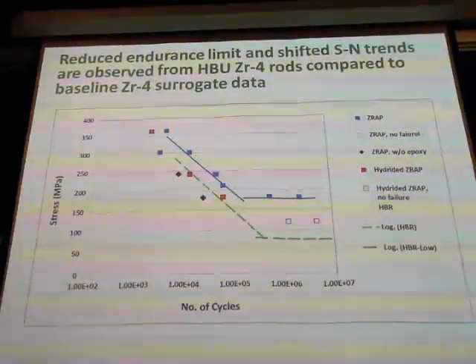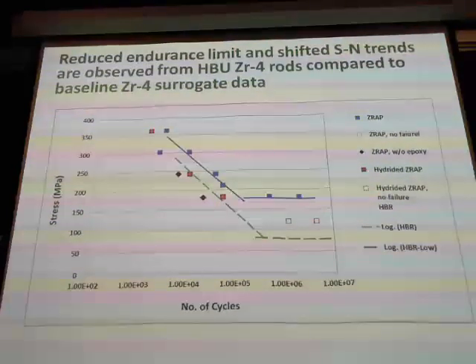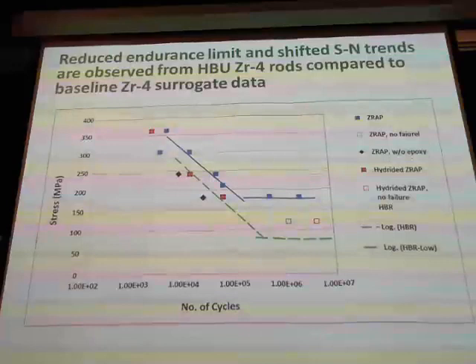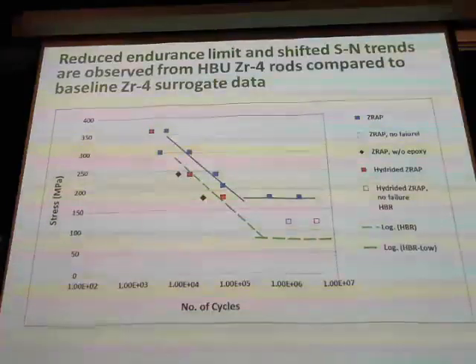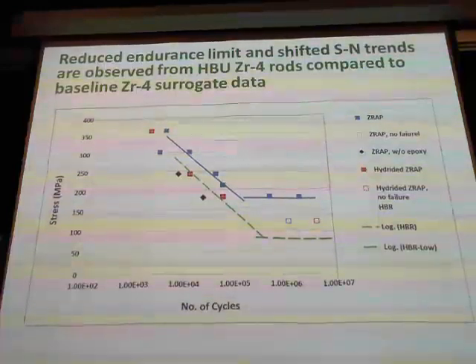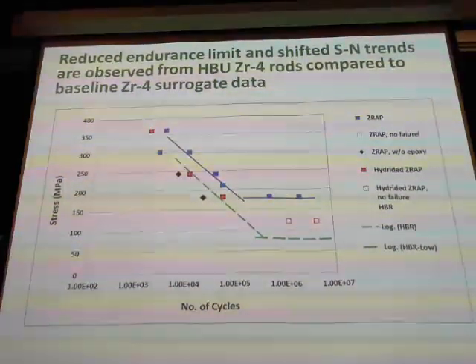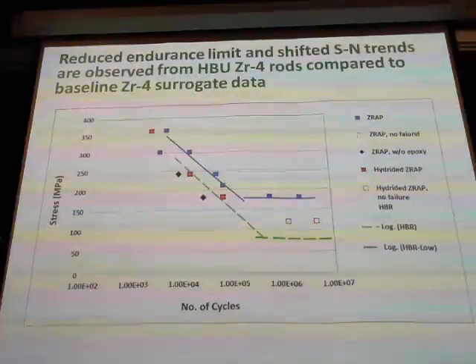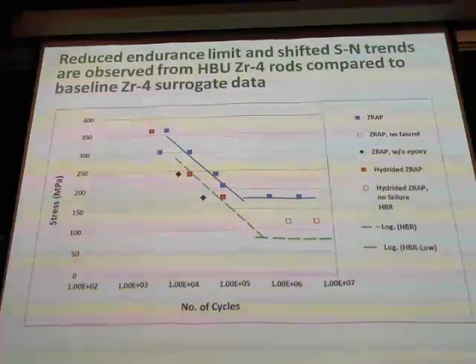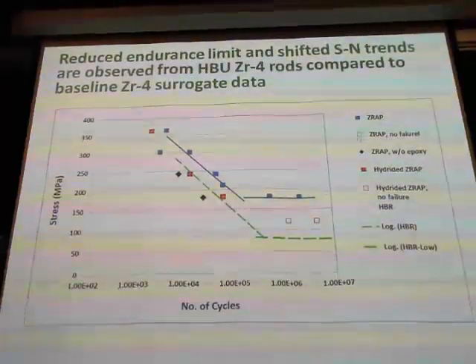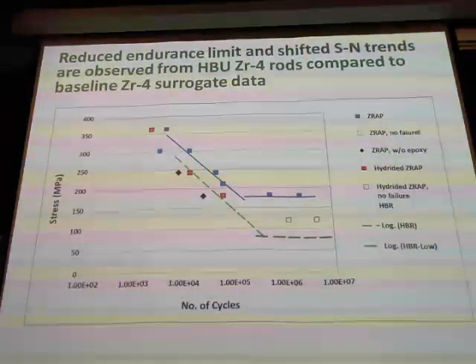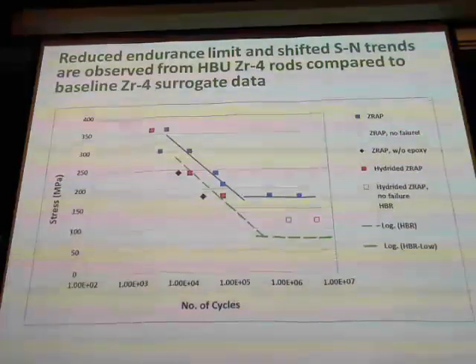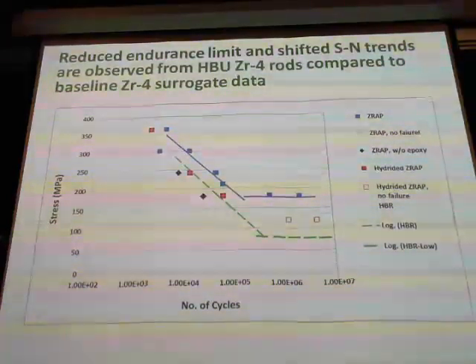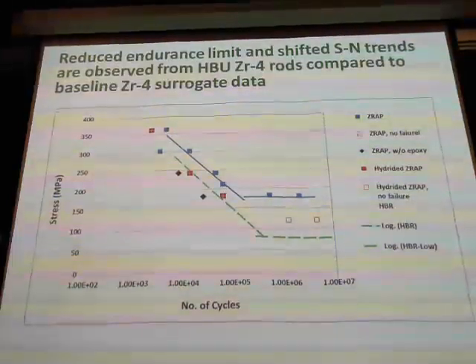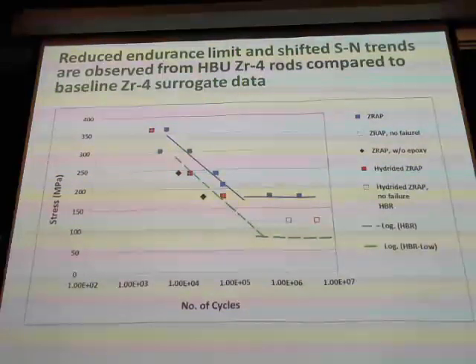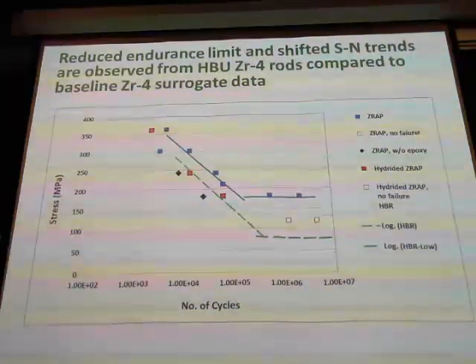Do you expect that fracture toughness reduces with the high burnup? Yeah, because of the high burnup. Even if you don't have the hydrogen, because of the high burnup in the periphery of the fuel, the ductility is reduced, right? Hardening is induced because the hydride rim forms. Because you always have oxygen and hydrogen in the reactive environment. So outside oxidation and hydrogen coming into your structure.